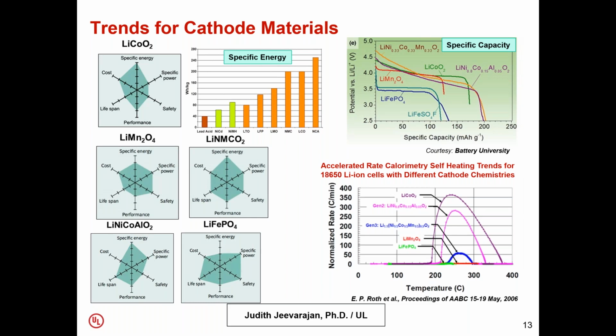The one on the bottom also is a figure that shows the accelerated rate calorimetry self-heating trends for some lithium-ion 18650 type cells that have different cathode chemistries. And what this shows you is that compared to a lithium cobalt oxide, which has a high self-heating rate, the lithium iron phosphate is very benign. It just says that in comparison it's benign, doesn't mean that a lithium iron phosphate is completely benign.